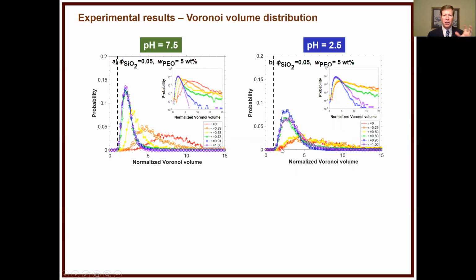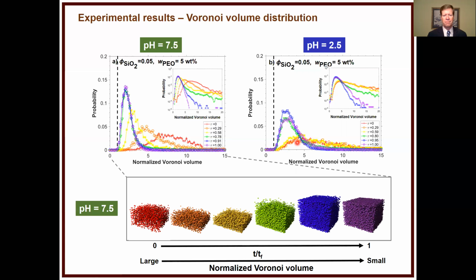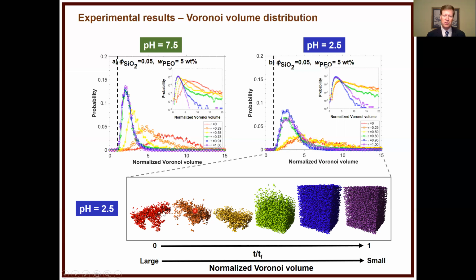So what we have here is bits of gel flowing around, and eventually you have enough capillary pressure to pull down and break those primary chunks. Just comparing to that movie, we have color-coded images of that video now, and comparing to the different distributions. So this red one goes with this wider distribution, this purple one goes with the end of time drying situation. And this is just like the video I showed you before. You can see, it just looks denser essentially as you go through. Whereas on the right-hand side, the microstructure is changing drastically, but it turns out the micro-scale microstructure isn't changing, it is breaking up in chunks and flowing, right? And then eventually the capillary forces. But if we had more polymer in here, we could arrest that microstructure. So it really depends on what density of particles and what you really need to have as a binder for your final, for instance, dissolution.